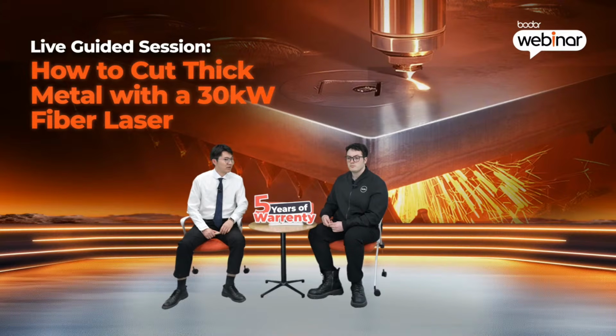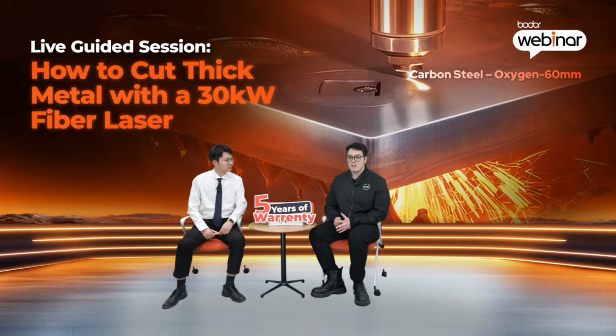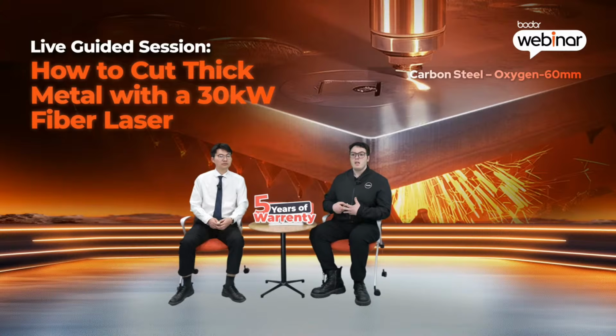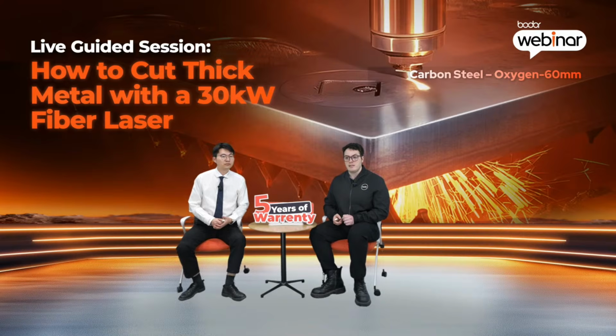Now let's see how this works with real thickness. Let's start with our thickest material, 60 millimeters carbon steel. At 60 millimeters, we usually start with positive focus, because at this thickness, the biggest challenge is not speed, it's stability. So the setup looks like this. The focus is set to 26 millimeters. The cutting speed ranges from 0.2 to 0.6 meters per minute. And we are using a single layer 2.5 nozzle. Lower speed helps the oxygen reaction stay consistent, and the smaller nozzle helps control the gas flow.